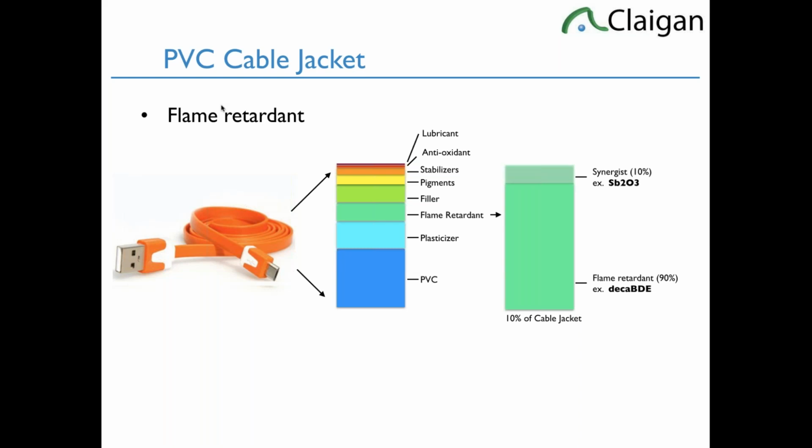And we see this with decaBDE, which is the only RoHS polybrominated diphenyl ether we ever really see. It's always present with antimony trioxide. With it present, you don't need nearly as much bromine flame retardant. And the bromine and halogenated flame retardants are very important types of flame retardants. They're all chemical gas phase.